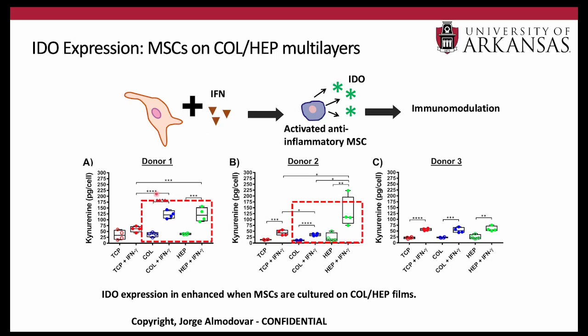And so what we see is that the expression of IDO is higher when the cells are exposed to interferon gamma. That's expected, but it's significantly higher when the cells are on our surfaces. And this was true for 2 out of the 3 donor cells that we investigated. So that was quite favorable as well. Again, heparin-terminated surfaces were our best surface, promoting a large secretion of this molecule.